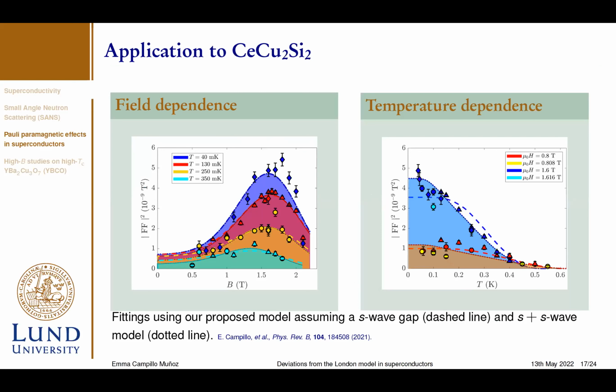And the important thing about this data is that there's a huge debate about what the pairing symmetry of the superconducting gap of CeCoIn5 is... of CeCu2Si2. It has been proposed by previous heat capacity measurements that the superconductor may have a double S wave gap. So we tried our model using different gaps, a single S wave gap and a double S wave gap. For our model, the double S wave gap works better than the single S wave gap, so we are confident to say that we agree with the results previously found by heat capacity measurements.